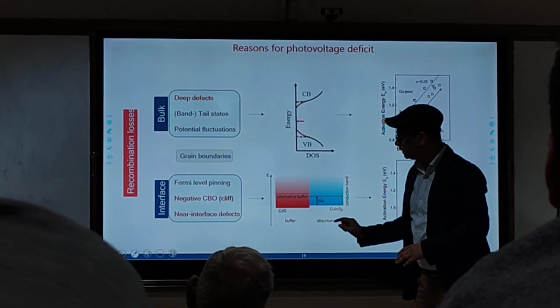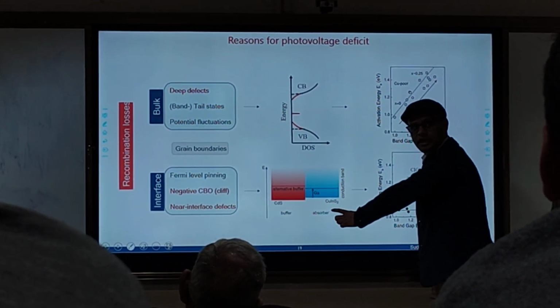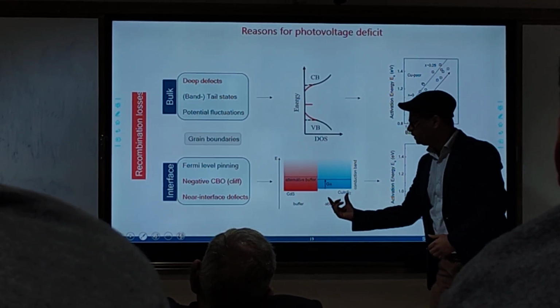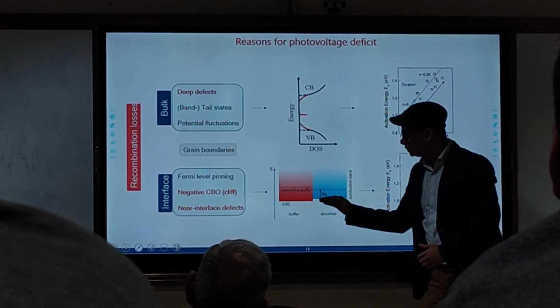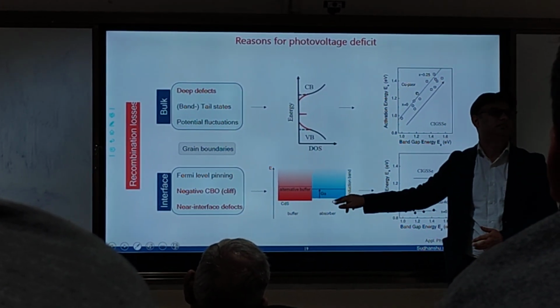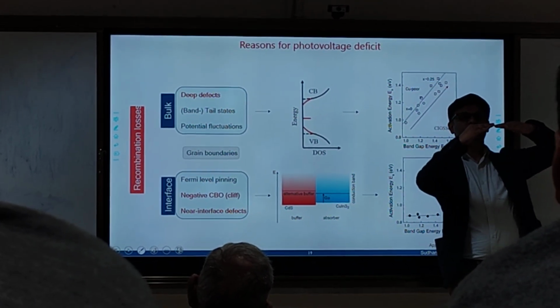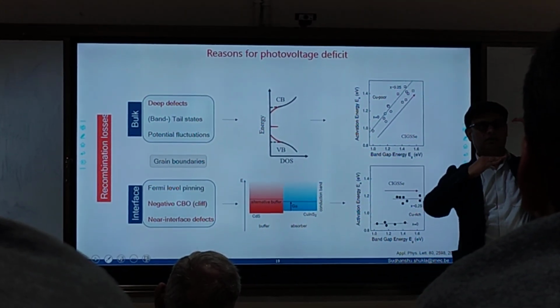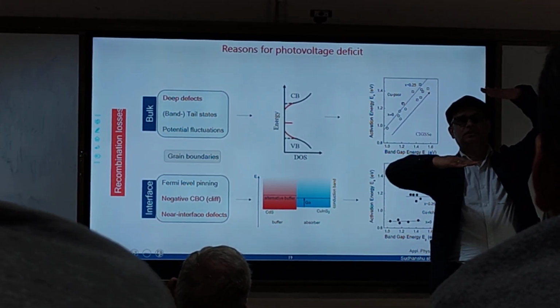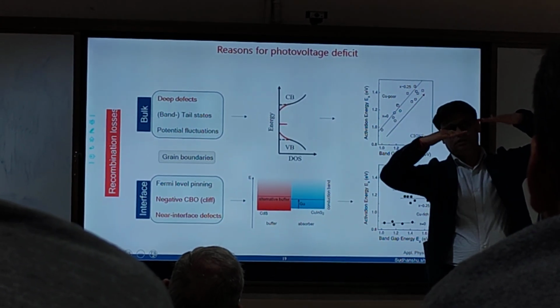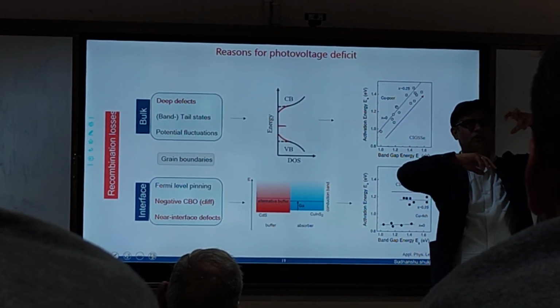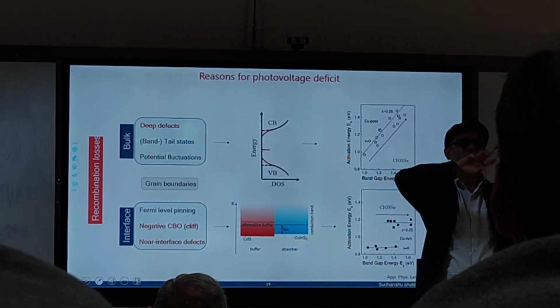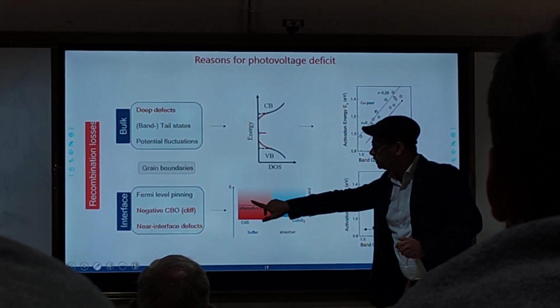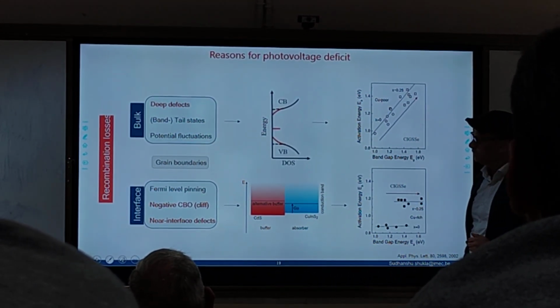And when it comes to the interface, you have material A, which is your absorber, and then you combine it with the N-type material. So this band alignment actually decides the recombination. So there should not be too much energetic mismatch. So material A and material B cannot have this scenario, this scenario. They should be more or less okay because the electron would like to go seamlessly from one material to the other. And that's where interface recombination kicks in.